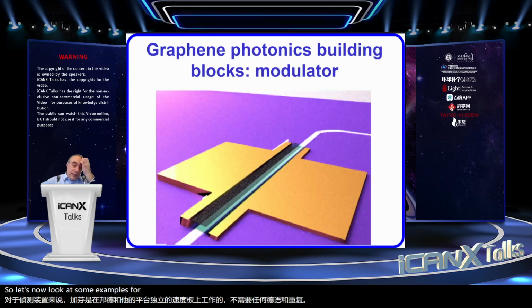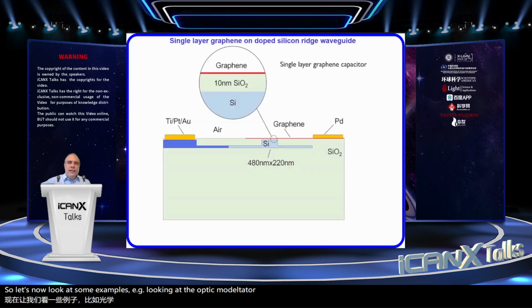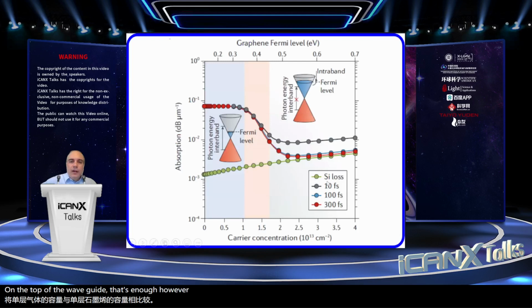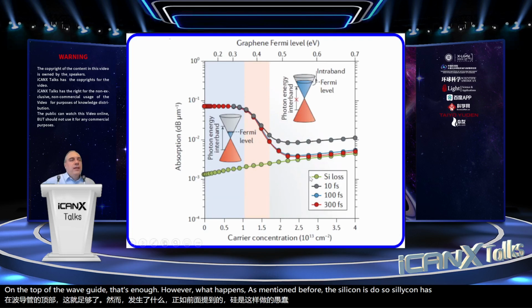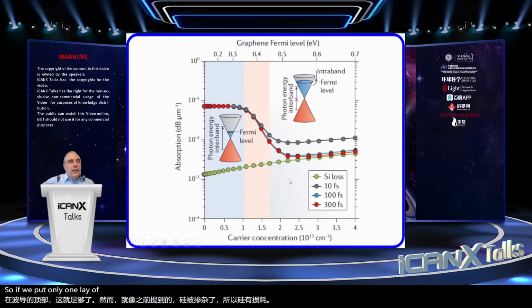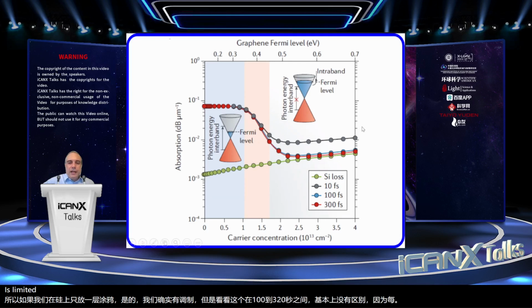For example, looking at the optical modulator, the very simplest approach is to have this single layer graphene capacitor, one single layer of graphene on top of a waveguide. That's enough. However, as mentioned before, the silicon is doped, so silicon has losses. So if we put only one layer of graphene on top of silicon, yes, we do have modulation, but look at this, between 100 and 300 femtoseconds, there's basically no difference because everything is limited by the silicon substrate.